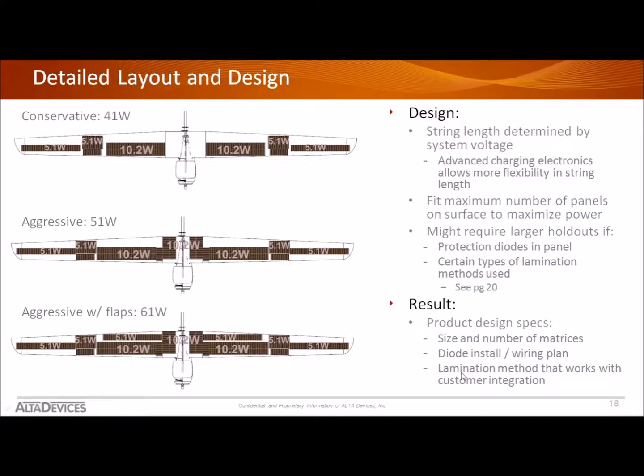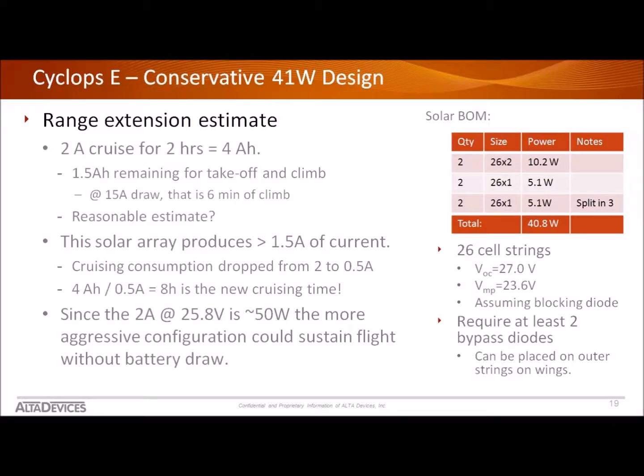So the result from the detailed layout and design is that we get the size and number of matrices, which would correlate with the cost, a diode installation and wiring plan, and then a lamination method that would work with the customer's integration. So for the Cyclops E, the conservative 41 watt design, here's the bill of materials for that, which would be 2 26 by 2 matrices, which generate about 10 watts, 2 26 by 1s that generate 5.1 watts each, and 2 26 by 1s that generate about 5.1 each, but these are the ones that are actually split into 3 parts. So our total power would be about 40.8 watts.